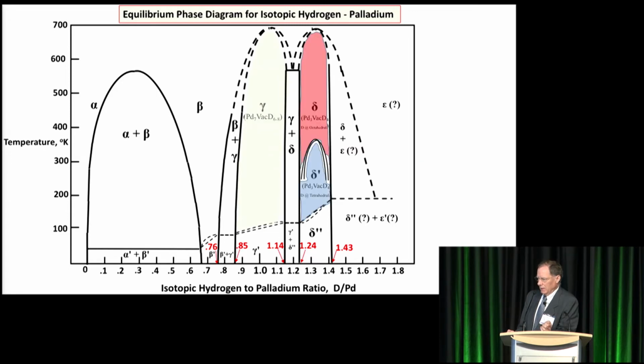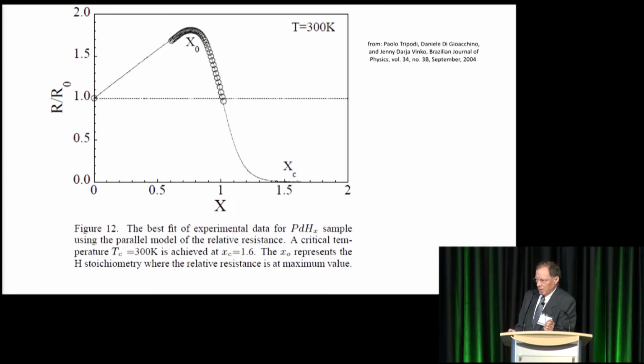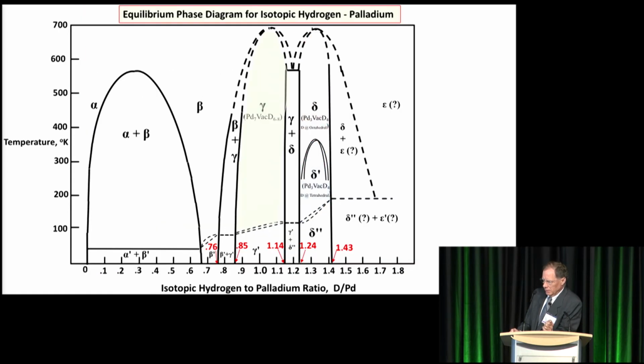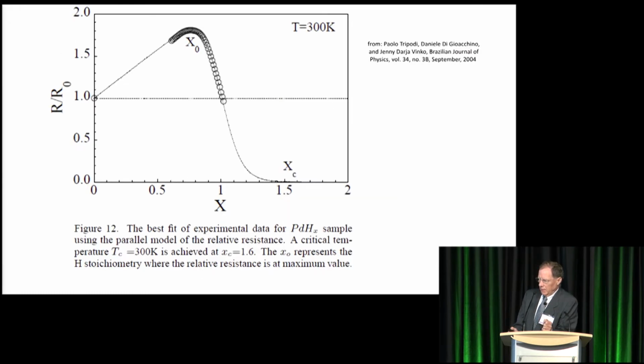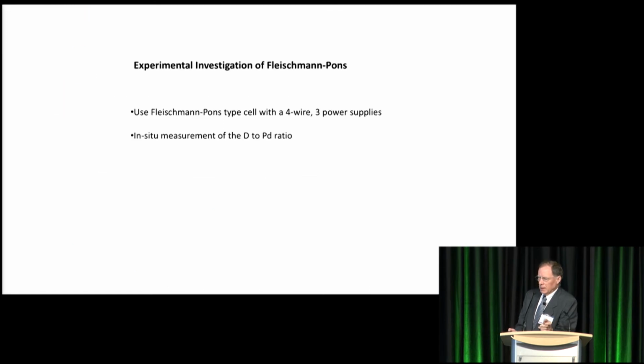But bottom line is that the yellow and the red and the blue are the two most important additions to the phase diagram. They are the equilibrium conditions. They're the true lowest free energy forms. And the problem is whether or not kinetically you can get there. And I think that's one of the issues that's been troubling LENR. I might just add that this area over here is still under a lot of speculation, but there's at least some support in Tripodi's work to indicate it happens at 1.6. But again, I showed it as a dotted line.